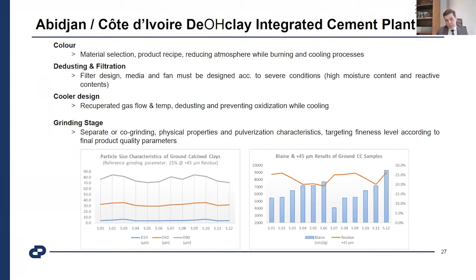And then, as I said, the grinding stage is critical because it's not a standard supplementary cementitious material like fly ash or steel slag or blast furnace slag. We are talking about raw clay, just removing its moisture, and it depends on the clay composition.